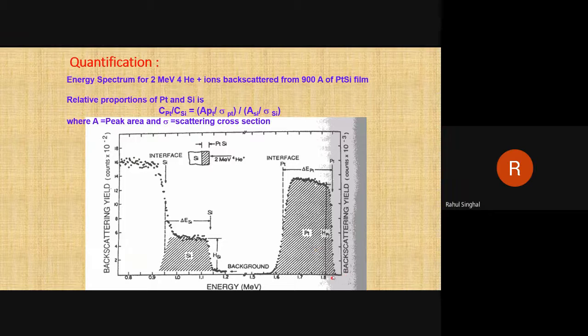So this energy, 1.8 or 1.9 obviously, and for silicon let's say 1.2 or 1.1, corresponds to the surface of the silicon, and the deep end of this peak corresponds to the interface of the silicon, like at this value, because silicon is present all over the sample. Now you will get a Gaussian peak due to the thickness of the film. And if you are able to find out the FWHM of the peak and do some back calculation, you can easily find out the thickness of the film.